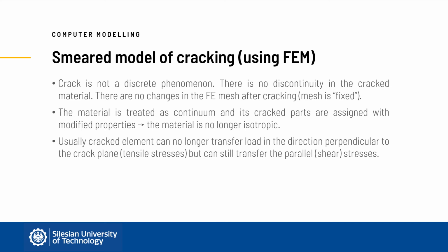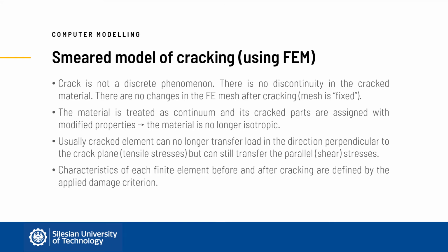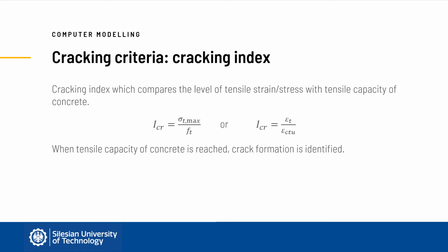Usually, the cracked element can no longer transfer tensile stresses, but can still transfer shear stresses. Characteristics of each finite element before and after cracking are defined by the applied damage criterion. The simplest way to determine whether cracking occurred is to compare the tensile strain or stress in the structure with the tensile capacity of concrete. The main challenge is to define this tensile capacity. If concrete in the whole analyzed element is assigned with uniform mechanical properties, the question usually is which tensile capacity should be chosen to represent cracking resistance of concrete.